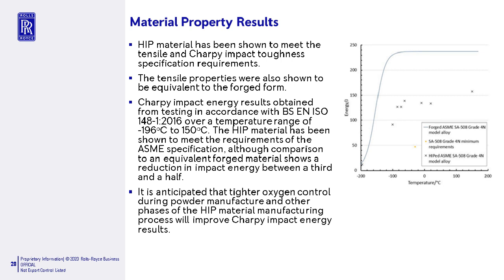and the HIP material has been shown to meet ASME, although comparison to equivalent forge shows we've got a reduction in impact energy. We believe we can improve those characteristics, and again by further oxygen control during powder manufacture, further controls and tweaks on the manufacturing process from filling through to packing through to the HIP cycle itself, we think we'll improve Charpy impact energy results up to equivalent to forging.